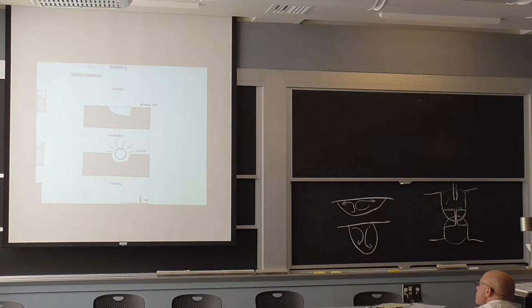Cavitation, a big problem in propellers. You have certain velocities, particularly on a propeller. On one side you're creating suction, and on the other side you're creating positive pressure. They have to kind of balance across that propeller to a certain extent. But on the suction side, you may get to the point where the water vaporizes, and you get little bubbles. And those bubbles, when they collapse, reach a singularity, everything coming to the center to a singularity point. You can get 10,000, 20,000 PSI pressures when that bubble collapses.